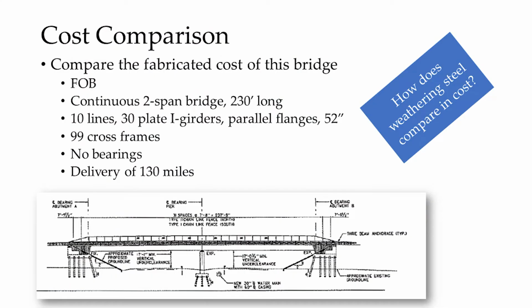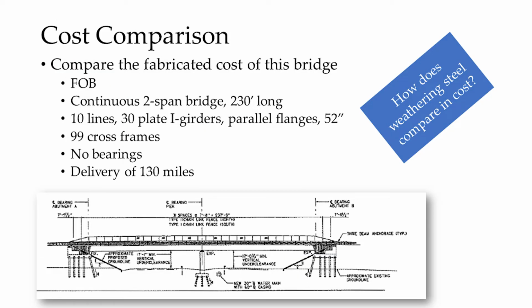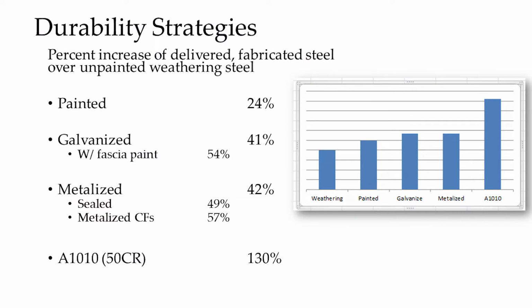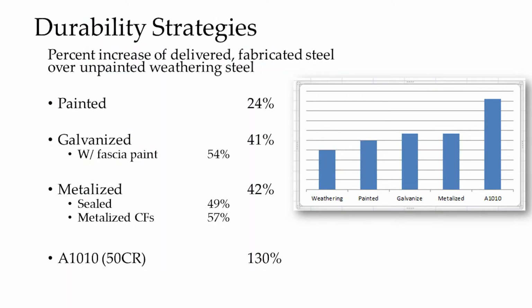In terms of cost, then, I've given you some factors in terms of the kind of things that would impact cost. We did a comparison back in 2017 to say, all right, how much more do the coating solutions cost? So we took this typical bridge and we estimated it as a delivered weathering steel bridge. And then we compared it with other solutions: 2-span bridge, 99 frames, 10 girder lines, pretty typical smallish steel bridge. So we looked at these strategies, and what we found was if you painted that bridge, that increased the cost about 24%. If you galvanized it, that increased it 41, metallized it 42, or 50 CR, which we had just done a 50 CR bridge for Virginia. That increased it by 130%.